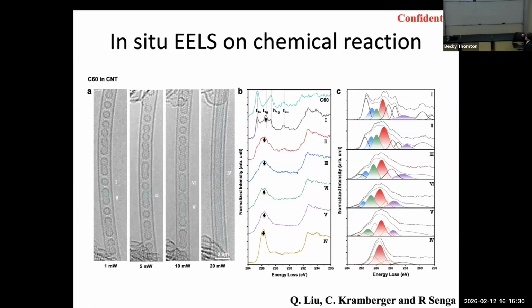It's a bit too complicated, so I won't say too much. But we can track all the chemical states during the reactions, because we are using pulsed lasers, and the spectroscopy is done at every 3 pulses or so. So we can get all the information. For the C60, this is a 0-dimensional carbon, so you have all the electron states like that. By the way, this has been taken from one molecule. Then you can have some dimers, and trimers, and finally we get nanotubes, which are 1-dimensional with different Van Hove singularities, different discrete energy levels.